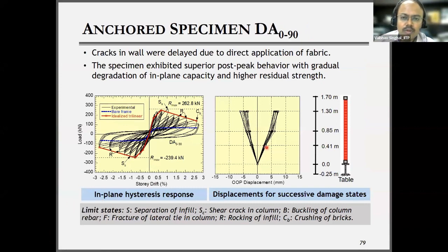Yes. So this is the response for the direct anchored. So direct anchored and the sandwich anchored have performed almost nearly the same. Again, for the direct anchored also, we could not see any separation of the wall from the RC frame. And the out of plane displacements were also significantly lesser compared to the unanchored or the control specimen.